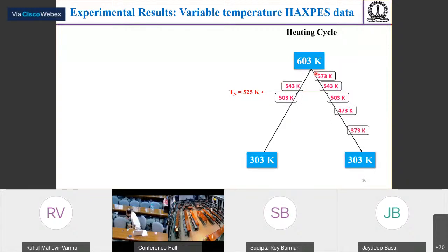Then we started cooling the sample in a stepwise manner down to room temperature and collected the core level and the valence band spectra at each of the temperatures measured here. Before collecting the spectra, we stabilized each of these temperatures by waiting more than half an hour at each point. After that, we again heated the sample up to the 603 Kelvin temperature to reproduce all the collected spectra at each of these temperatures.